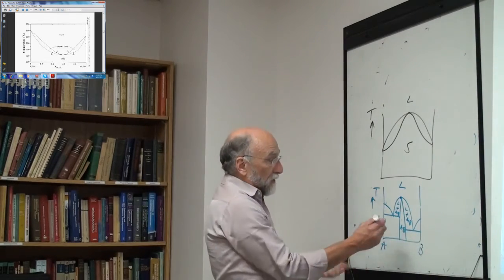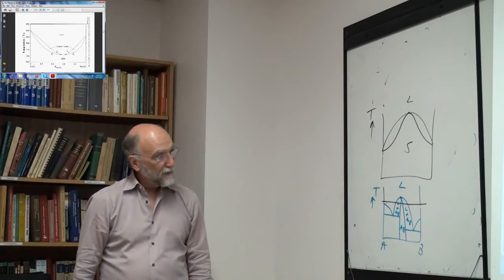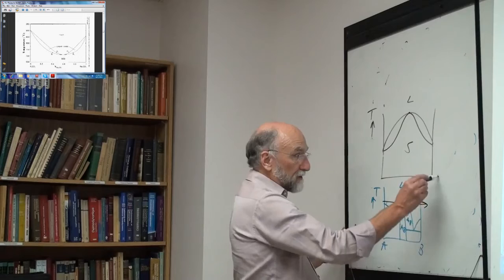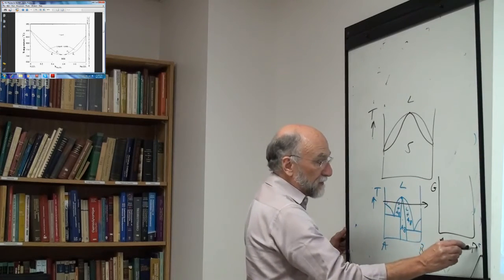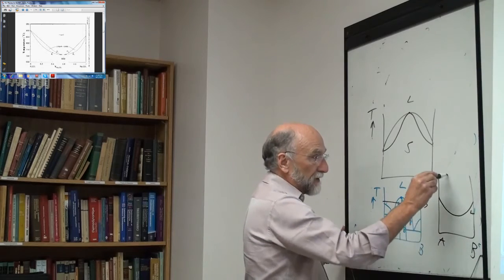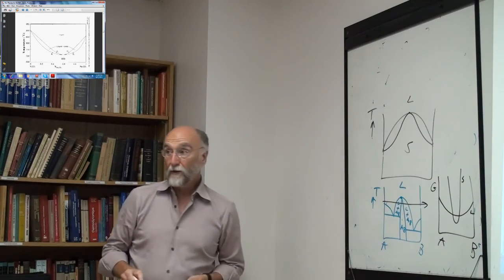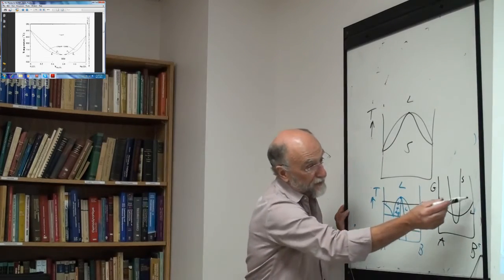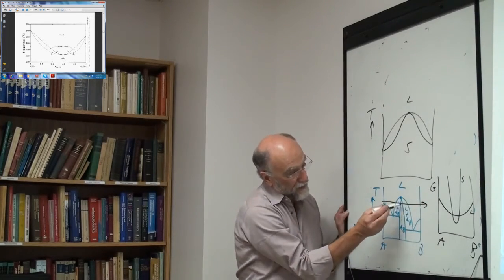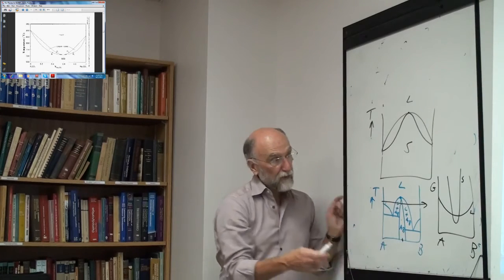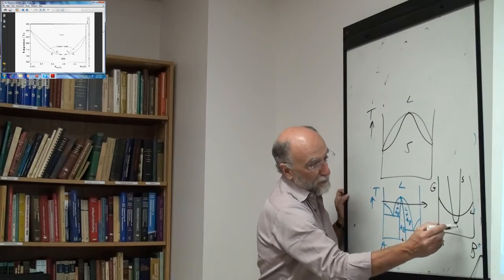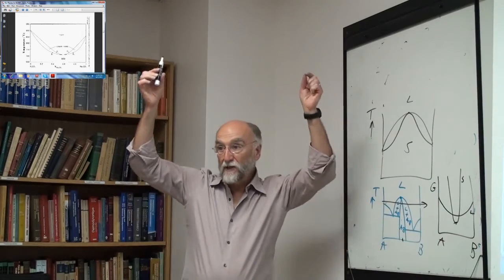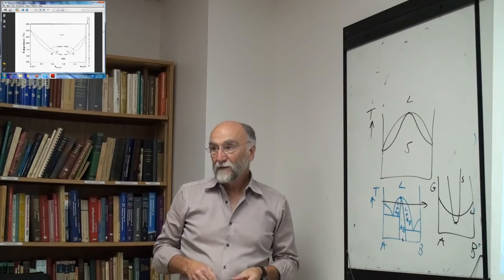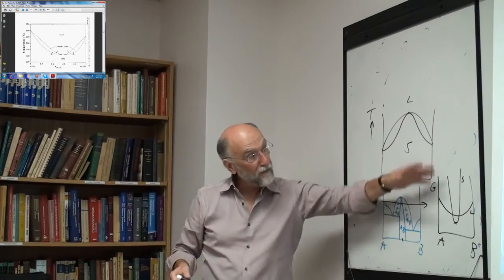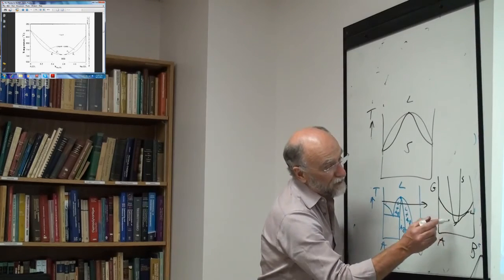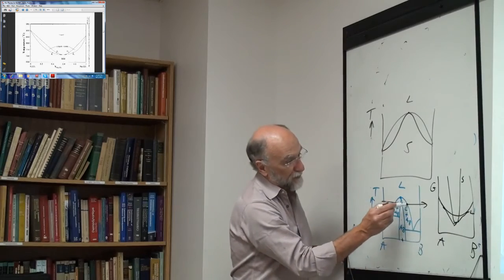If I were to take this diagram and go across at this temperature here, and at that temperature I draw the Gibbs energy composition curve, I would find the liquid phase went like this, and the solid phase went like that. The liquid phase is more or less normal. The solid phase is strongly stabilized around that composition where you have AB, AB, AB. But as you get away from that composition, its Gibbs energy goes up. It's stabilized because you have A's next to B's. If you start to get away from that composition, it goes up. Now you have two common tangents, which give you the